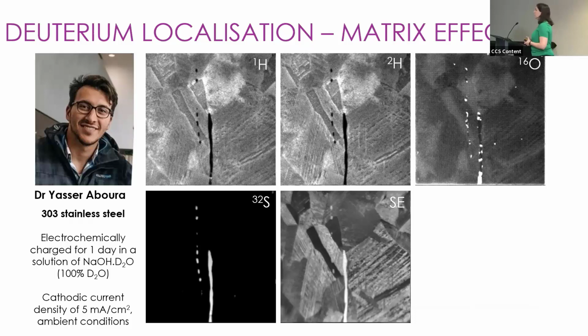And what we thought we would start with was alloy 303 stainless steel. Alloy 303 has a lot of manganese sulfides in it. And we thought, from reading the literature, manganese sulfides are supposed to be a location of hydrogen trapping. So we thought, great, these would be really easy to identify. We'd see hydrogen localized in or around them, and then we would know what we can and can't do with the NanoSIMS.